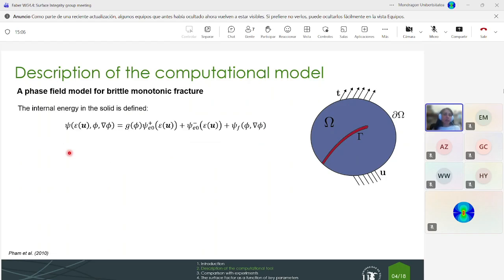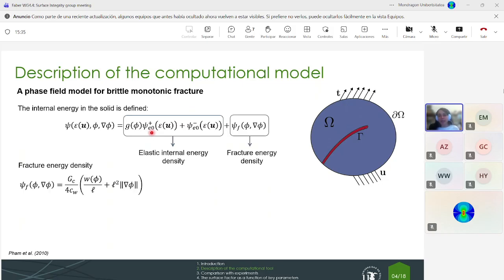The internal energy can also be defined as the sum of different terms. The first one is the elastic internal energy density, that you can see is split into two additional terms. This is to consider the fact that only tensile strains promote failure, not negative compression strains. And this is the reason why we have a degradation function only multiplying the positive split term of the energy. And then we have the fracture energy density. So the idea of fracture energy density was introduced by Griffith. It was GC, a material parameter that is the critical energy release rate, multiplied by the crack surface.